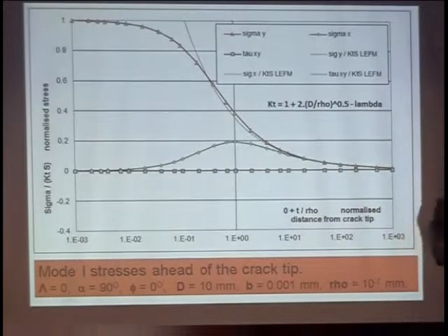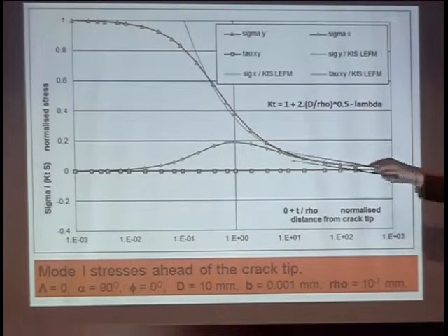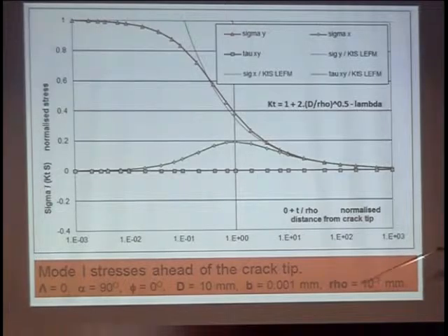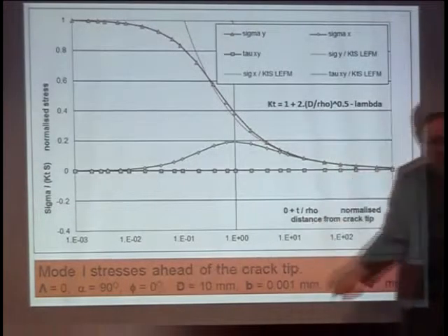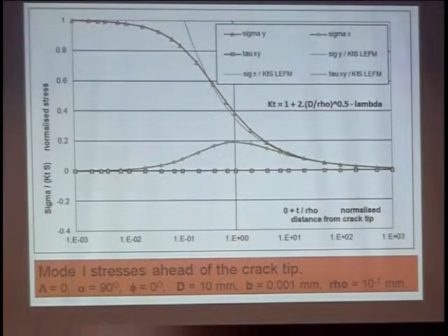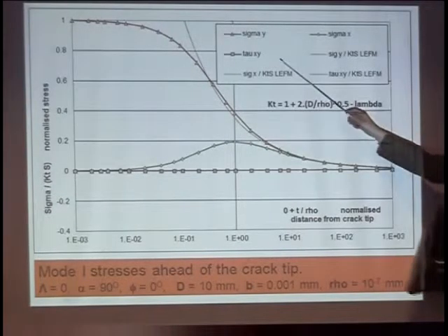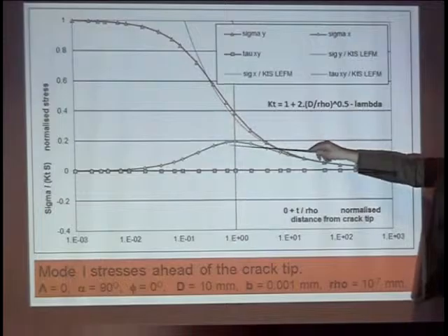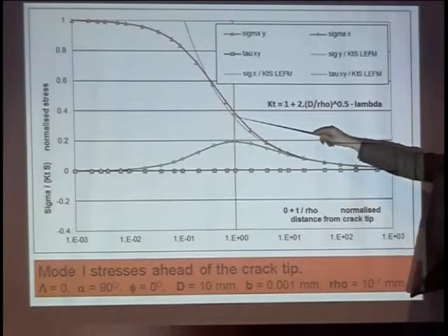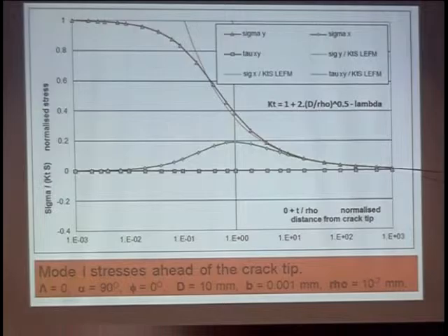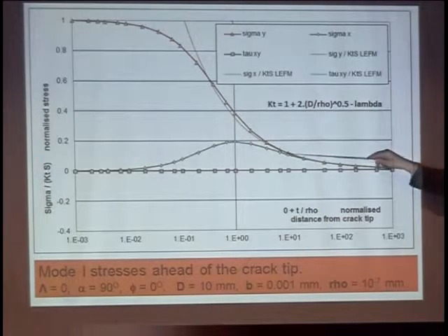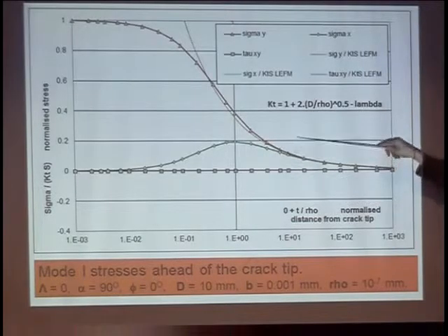Sigma x and sigma y are exactly the same line. One of the problems with the Westergaard solution is that it says sigma x and sigma y are equal, if we are on a line straight ahead of the crack. Here phi is 0, so we're looking at the line straight ahead of the crack. In our solution here, though, we find that sigma x, which is green, is completely different to the red line, except over here, and this is where LEFM is valid. We get breakdown of linear elastic fracture mechanics formally about here at a ratio r over rho of about 10.